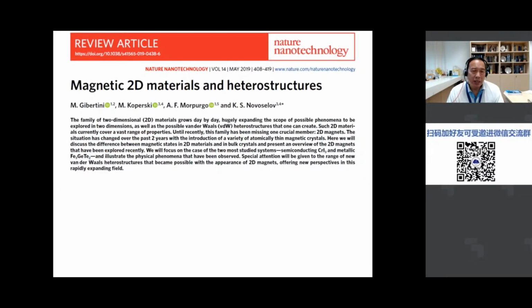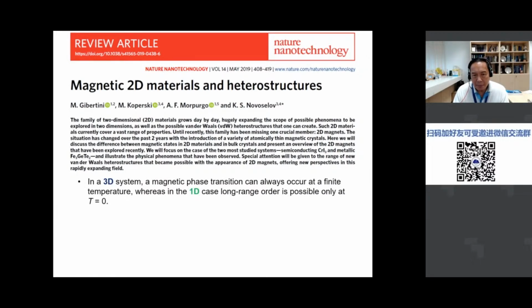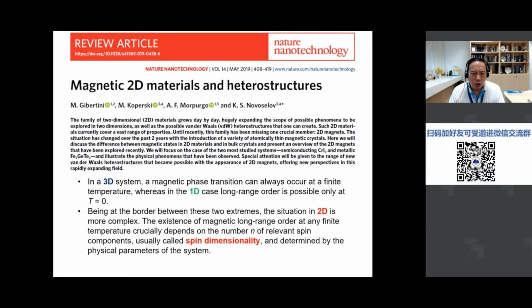Another review that came out just last year was by the group of Kostya Novoselov, who's now in NUS. So essentially, they summarized the field at that point in time and emphasized that in a 3D system, a magnetic phase transition can always occur at a finite temperature. So you always see a Curie temperature transition in the 3D system. On the other hand, in a 1D case, you can only get long-range order at 0 Kelvin. In other words, you can't get long-range order at room temperature. And the 2D is complex. It's in between 3D and 1D. And the existence of magnetic long-range order at any finite temperature depends crucially on the number of spin components, usually called the spin dimensionality, and determined by the physical parameters of the system. So what does this mean, spin dimensionality?